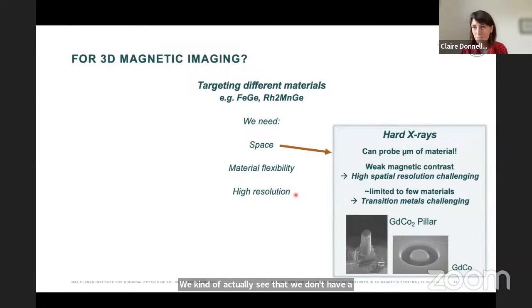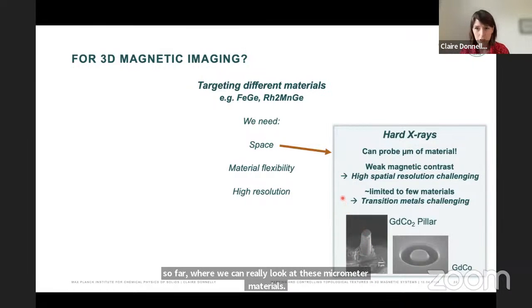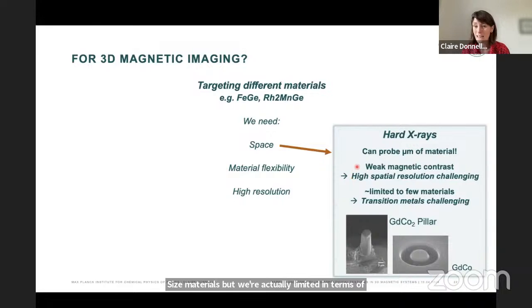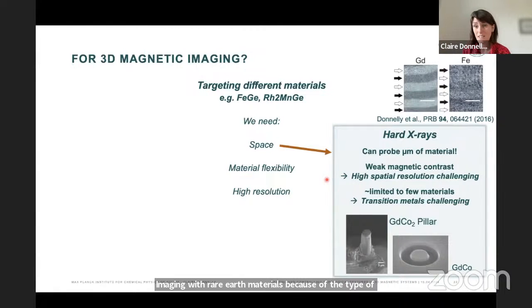So on the one hand, we have higher energy X-ray imaging, such as I've shown you so far, where we can really look at these micrometer-sized materials, but we're actually limited in terms of which materials we can look at. So you can get very nice imaging with rare earth materials because of the type of dichroism that we get at the rare earth edges. But when we go to transition metals, we have almost no contrast whatsoever, significantly weaker contrast, which makes the imaging in 3D particularly challenging. And you can see this demonstration on the top right here.